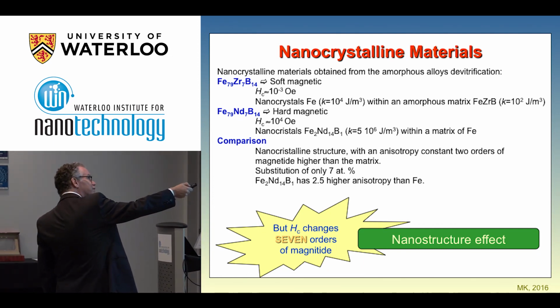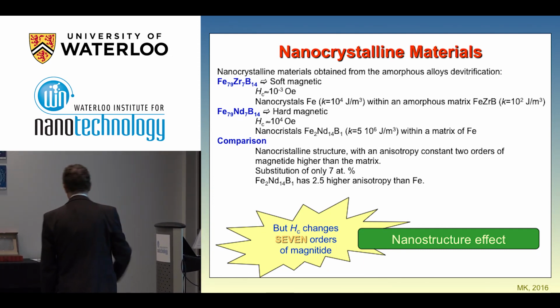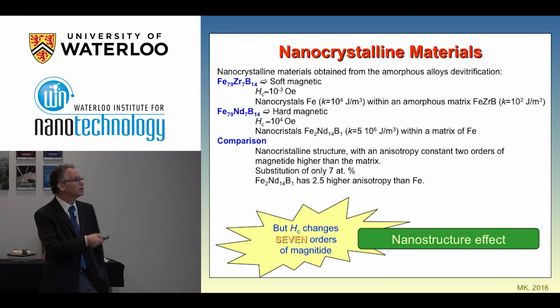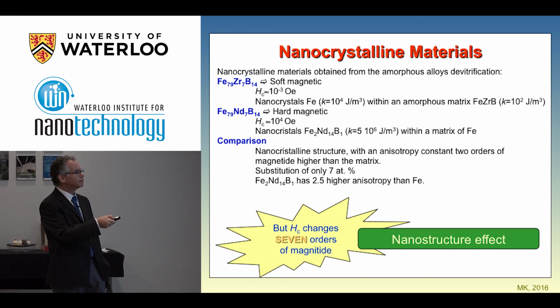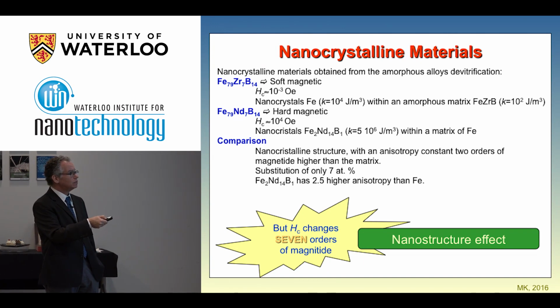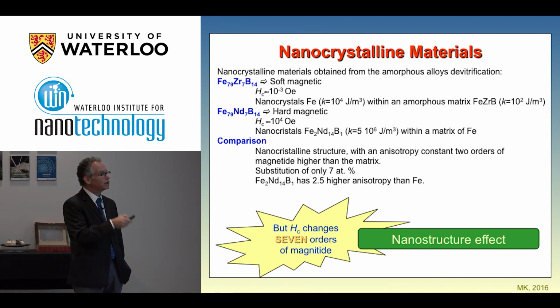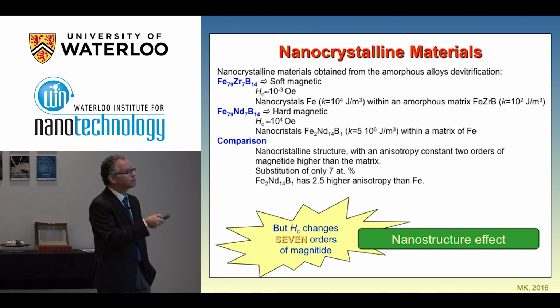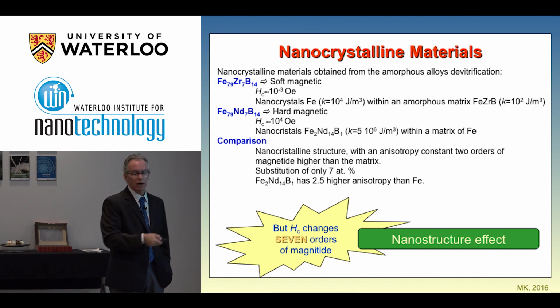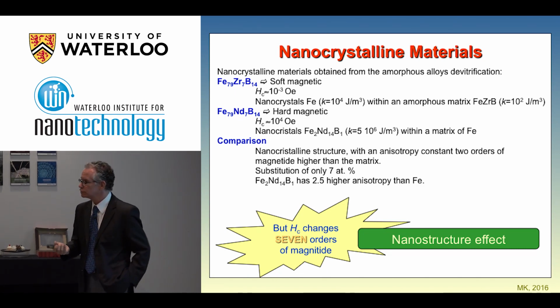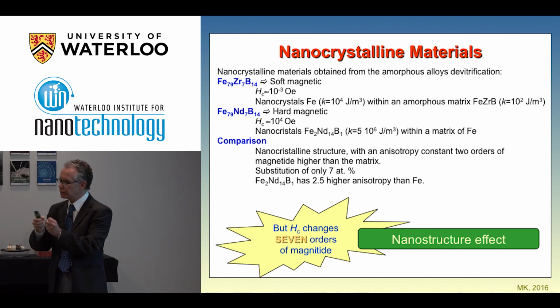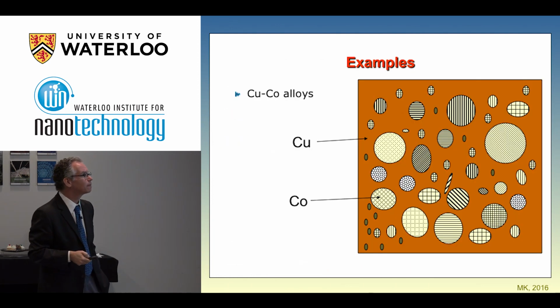And just by changing 7% of this composition, you change the zirconium by neodymium, you change this material completely by 7 orders of magnitude in coercivity. So this is extremely hard magnetic material, and all of this happens because of the effect of the nanostructure. So the coupling and decoupling within the nanostructured materials.